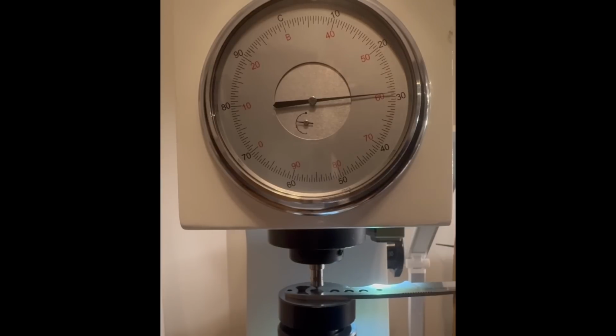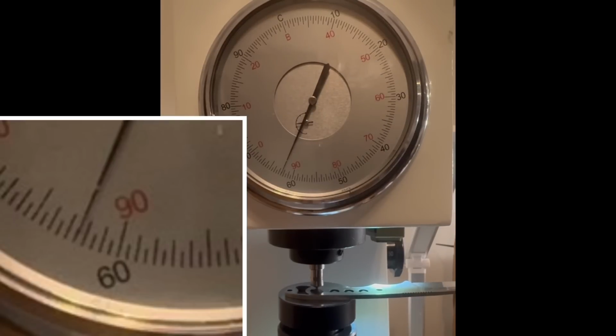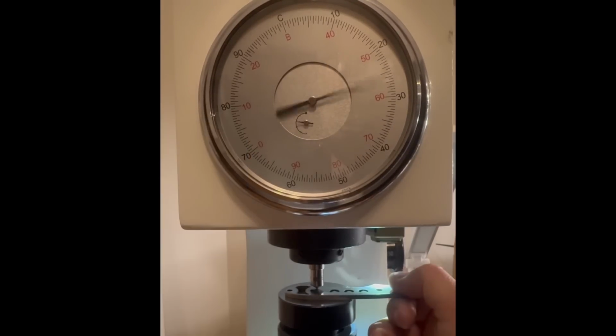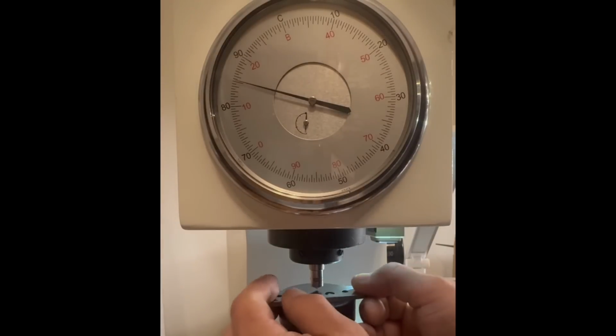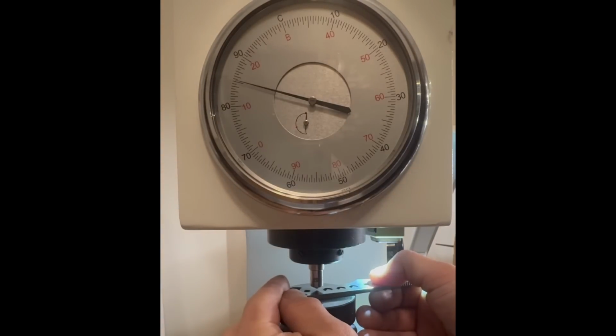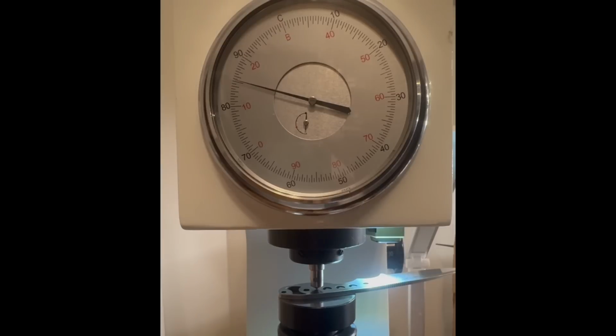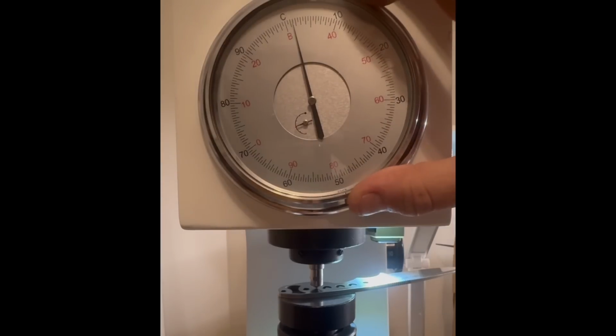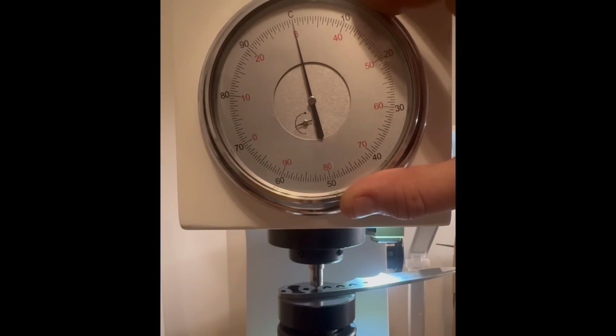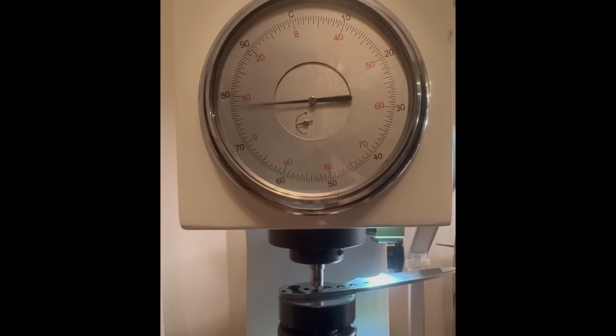And on this Rockwell tester, I am getting 62.4, 62.5 HRC, which is significantly above my Leeb test, but also below the advertised range, which was 63 to 64 HRC. Let's do a couple more pokes and see what the average is. A couple of points to make here. Will MagnaCut at 62.5 perform worse than MagnaCut at 63 to 64? No, it will not. Not to the point where you will be able to tell the difference.